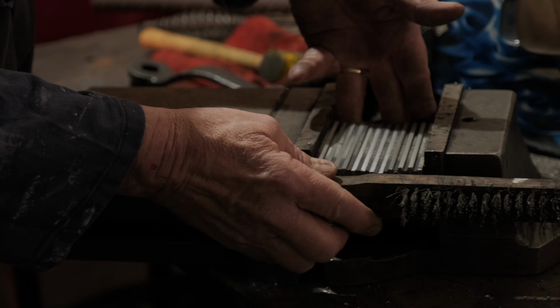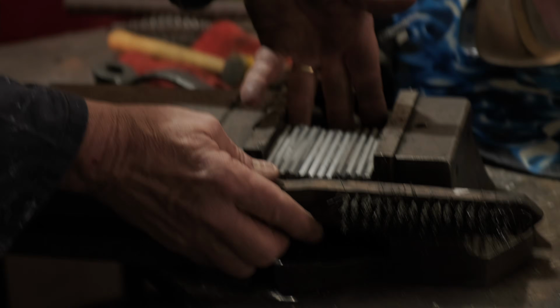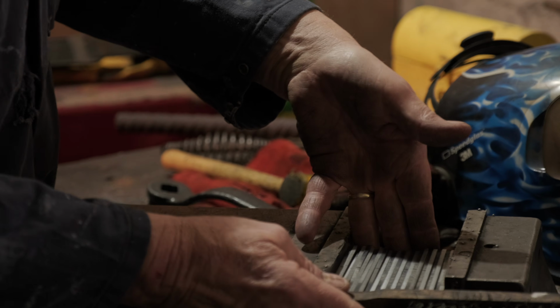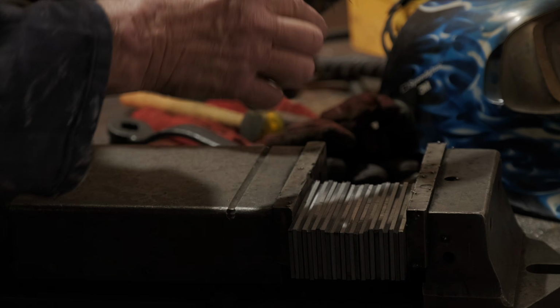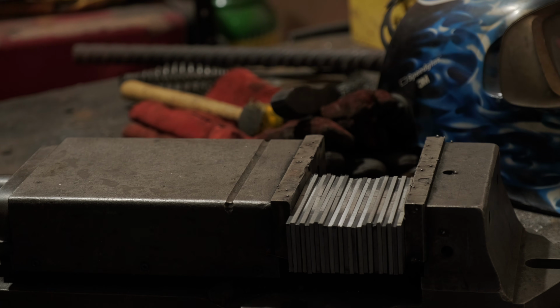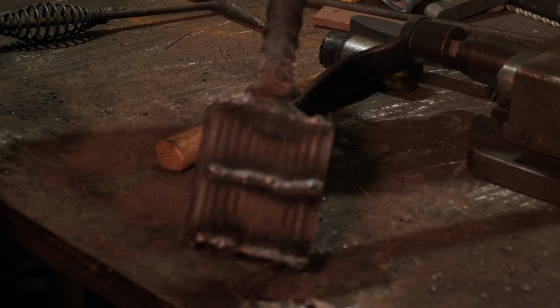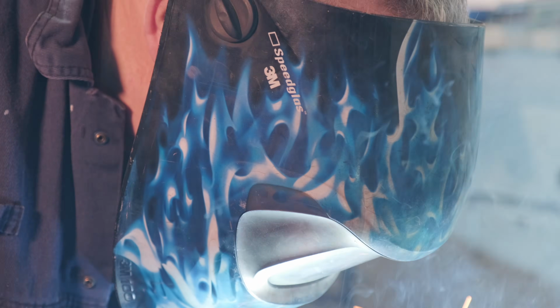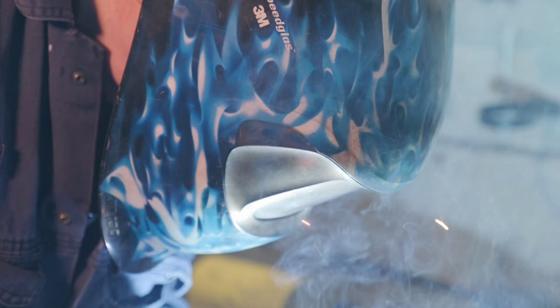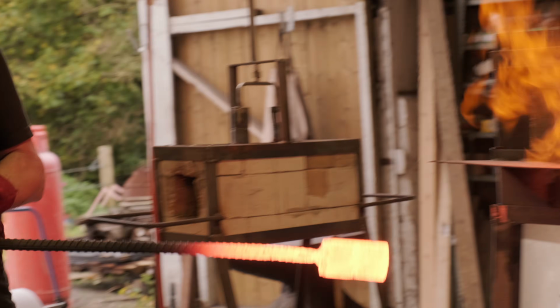Weld the stack up. Now, when I put the stack together, I put all my layers in an old machine vise. The kind of things you see on a milling machine that are very, very strong, and you can wang up that handle. I do it with a hammer, very, very tight. So you're squashing those surfaces flat together as much as you can. And then weld down the corners or on the ends, any kind of welding, MIG welder, stick welder, doesn't really matter. Weld a little piece of, I use a bit of rebar which I put on the end to make it into a billet that I can handle in and out the furnace.